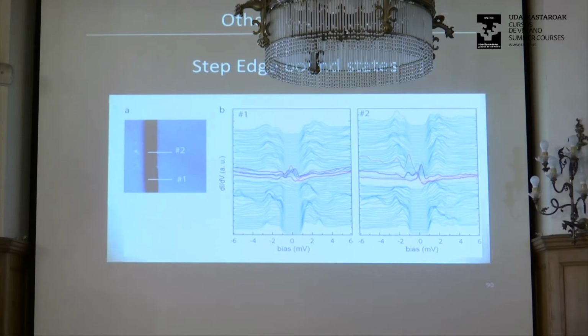Now, just to contrast this with another one-dimensional feature, we often see step edges in these systems. If you were to take spectra across a step edge, far away you see the nice superconducting gap. Right at the step edge, what you see is a bunch of peaks inside the superconducting gap, right? So you can see all these peaks. This is right at this edge. And this is another line cut. Again, you see a bunch of peaks. So this is very common in these kinds of superconductors.